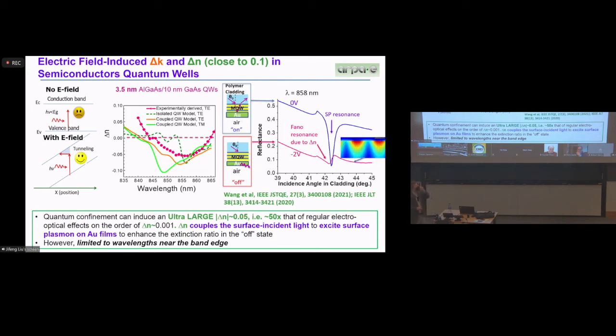So essentially, this is a process where you can change a semiconductor material from transparent to opaque near its band gap. This is how we change the refractive index of the material. And if you put this in a sandwich of what we call a quantum well structure, one with a bigger band gap and one with a smaller band gap, you can confine the electrons and holes in the smaller band gap region. This effect is even more pronounced, and you can reach a change of refractive index on the order of 0.1.